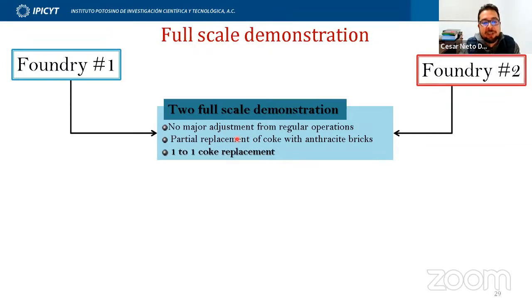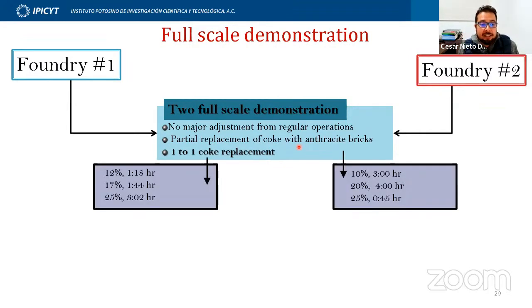Essentially, we didn't make any major adjustment to the operation. We just used the same operation as the regular conditions the foundry people were using. We used a partial 1-to-1 replacement of the coke by the anthracite briquettes. 1 ton of coke was replaced by 1 ton of anthracite briquettes. In Foundry 1, we reached up to a 25% replacement for 3 hours. And in Foundry number 2, we did a 25% replacement of coke by anthracite briquettes, and that lasted for 45 minutes.